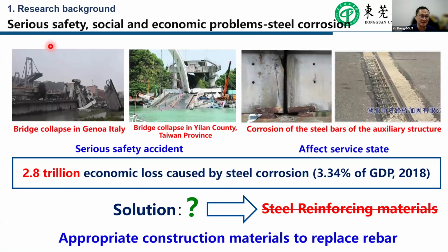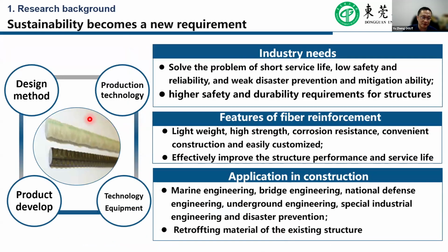As well, it's evident that the corrosion of the steel reinforcement inside concrete has caused some serious safety, social, and economic problems. In China, a 2.8 trillion RMB economic loss is caused by steel corrosion, which is around 3.3% of the GDP in 2018. Therefore, how to solve that? Maybe you can use some alternative construction material to replace the steel rebar. If we use fiber reinforced polymer reinforcing materials, that could be an effective way to solve the problems of short service life, low safety and reliability, and weak disaster prevention or mitigation ability, and high safety and durability requirements can be achieved.